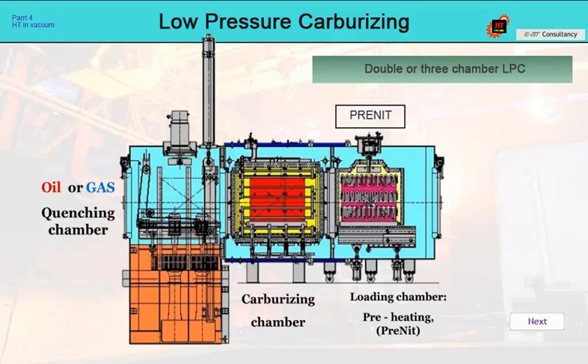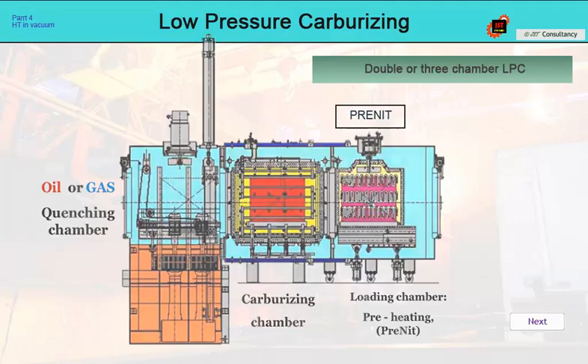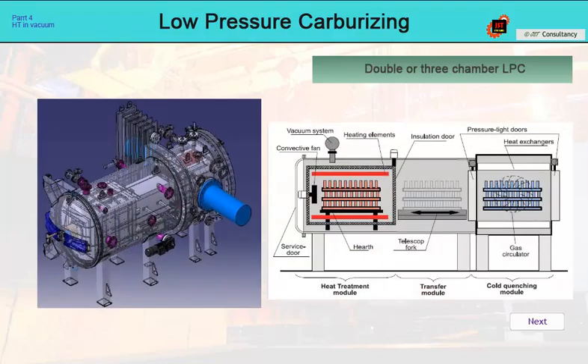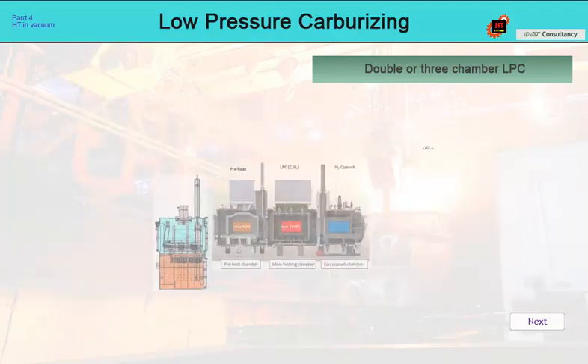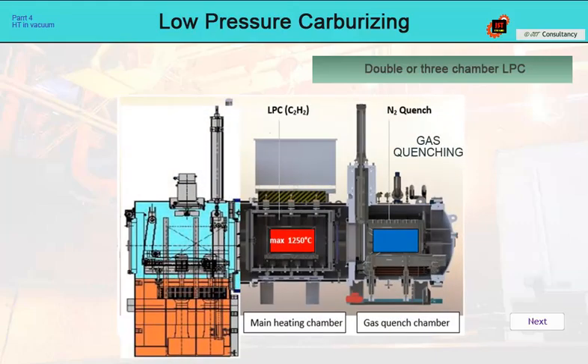For example, in Seco Warwick, it is used for applying the preheat process, in ALD or TAV as a transfer chamber when handling the charge between the heating and quenching module. A concept can also be accepted where one end chamber is for gas quenching, the middle chamber is for carburizing, and the other end chamber is for oil quenching. The batch is always loaded through the nitrogen quenching chamber, but after quenching it is taken out, depending on which quenching method was applied.